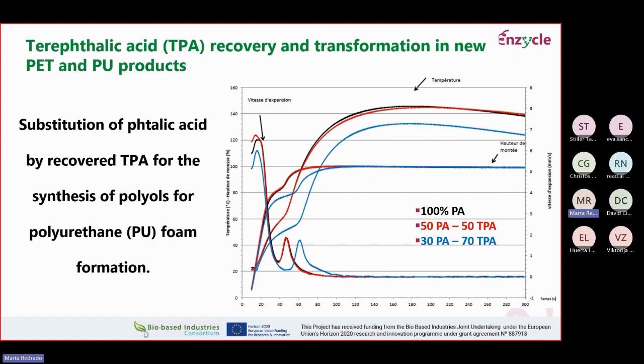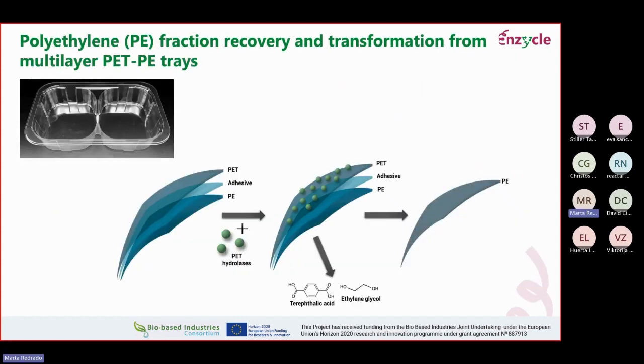What we have seen is that when we substitute 50% of phthalic acid for terephthalic acid, we obtain a polyurethane which has the same characteristics as the 100% phthalic acid. So we are using this recipe to produce polyurethane containing recovered TPA from the depolymerization process. And as I mentioned, we have also focused on the depolymerization of PET polyethylene trays.